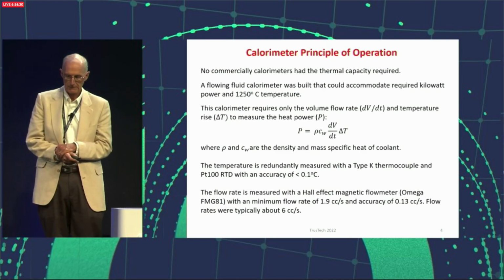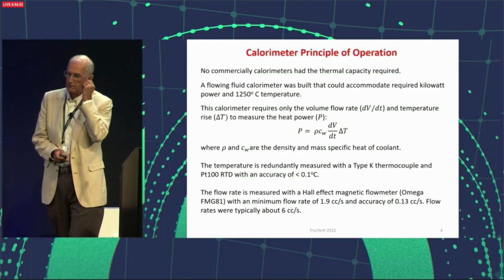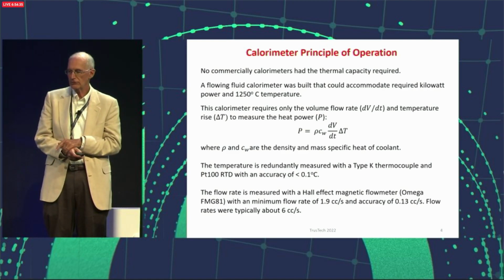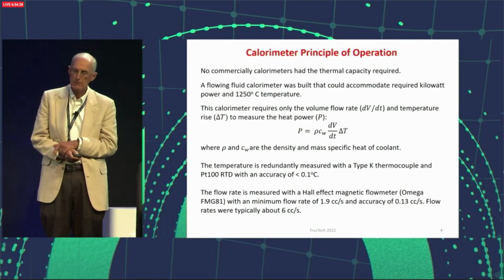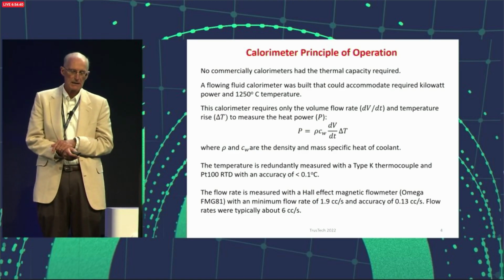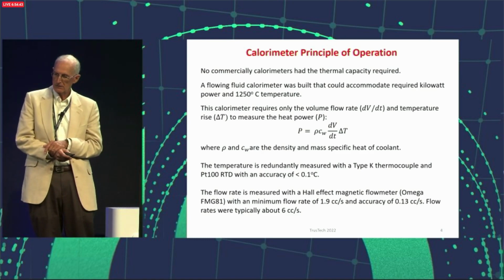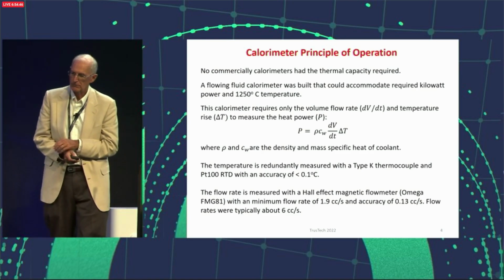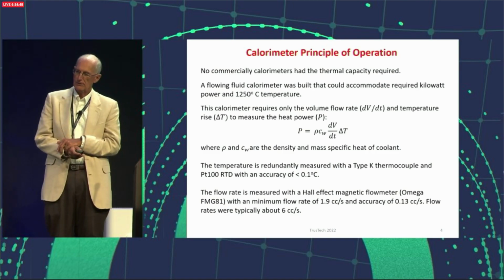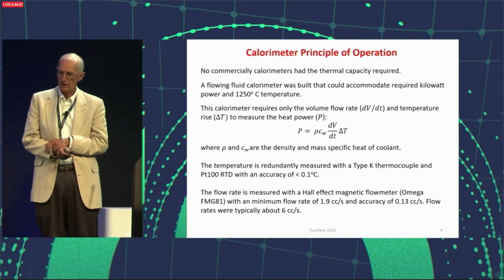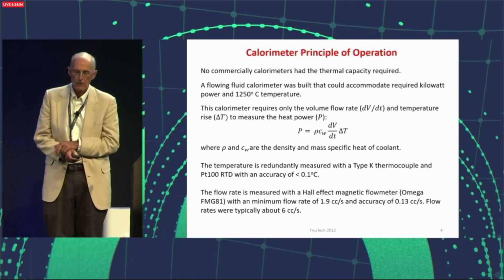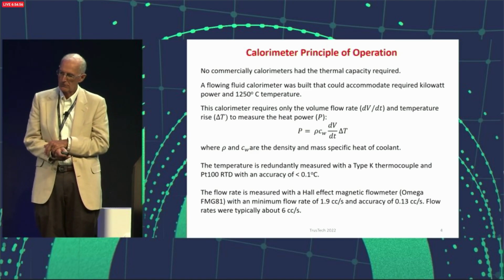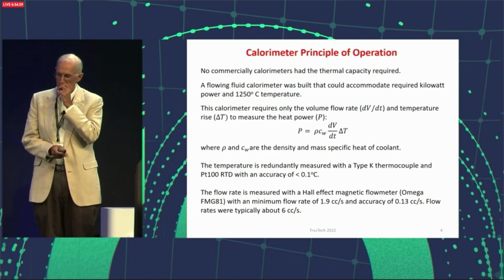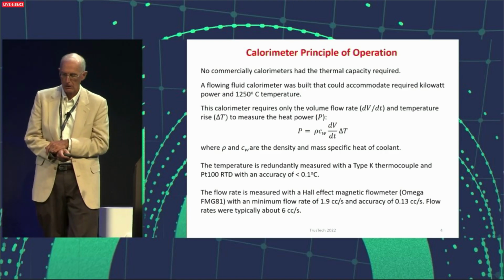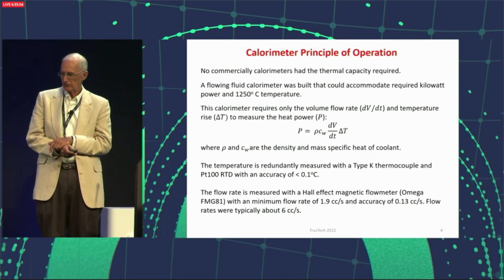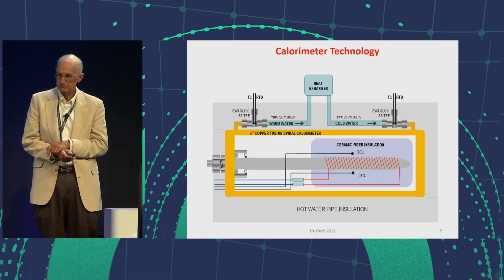There were no commercial systems available, so I developed a flowing fluid system that required just two measurements: the temperature difference of the fluid into and out of the calorimeter, and the flow rate. In this system, I redundantly measured the temperatures with a type K thermocouple and a platinum RTD with an accuracy of better than 1/10 of a degree C. And the flow meter was an Omega Hall type flow meter that had a sensitivity of 0.13 cc per second.